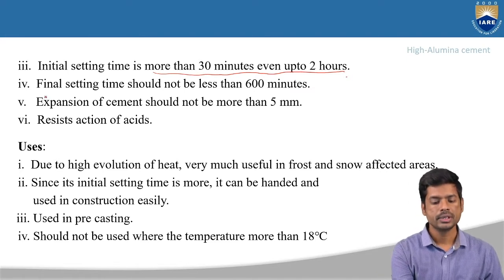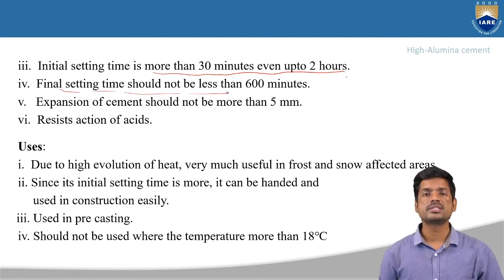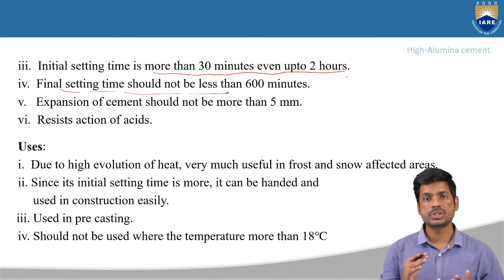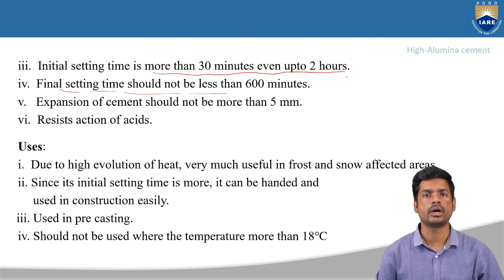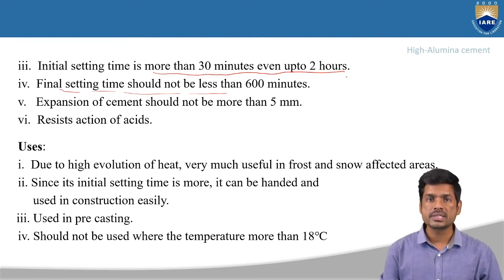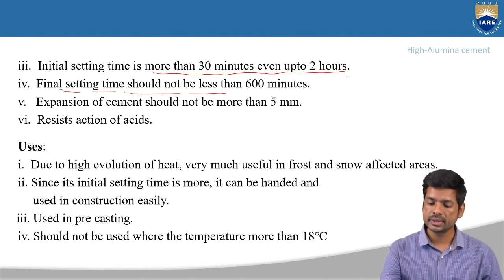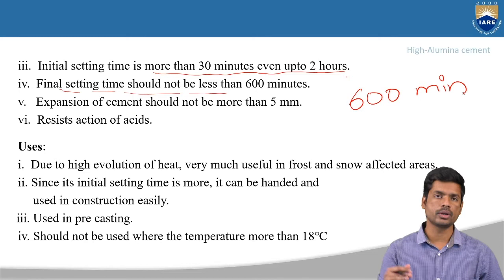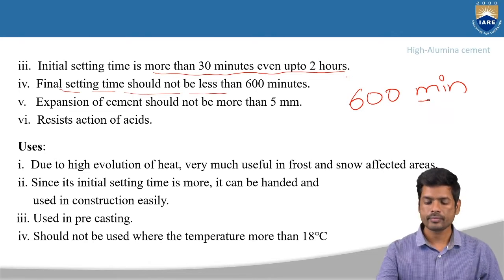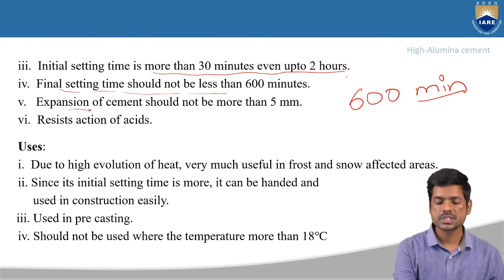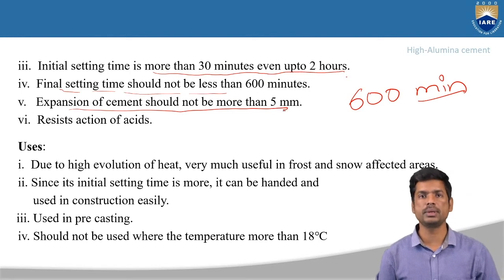Next, the final setting time should not be less than 600 minutes. Whenever you check the final setting time of high alumina cement, it should not be less than 600 minutes, meaning it should be greater than 600 minutes, around 10 hours. Next one, the expansion of cement should not be more than 5 millimeters.